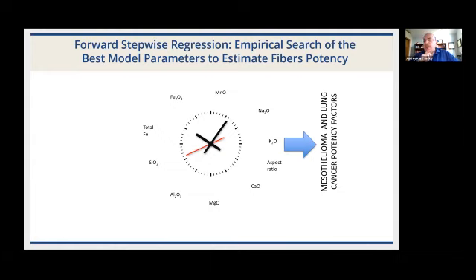In 2018, 2019, we used the following method. We put different elements of chemical composition of various types of fibers. We also used a very important parameter, aspect ratio. So it's a length divided by width of fibers. This is kind of the parameter of the elongation. And when we put all different parameters into the modeling tool, a computer statistical tool, we then determined the parameters that would allow us to predict carcinogenicity of specific types of mineral fibers.